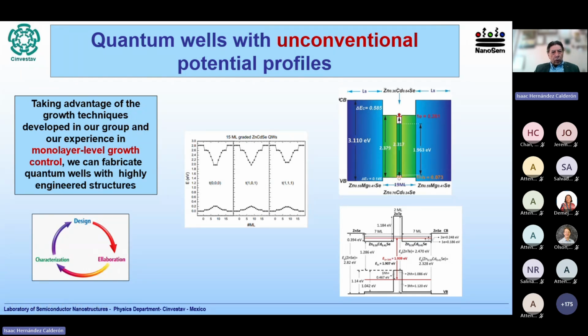So typically what we do is we say we want to have a heterostructure, a quantum well with this kind of specific properties. So then we make a design, we have a methodology, we make calculations, we try to make a design of the heterostructure. Once the calculations indicate that it could be a good structure, then we elaborate it. We do the growth by epitaxial techniques and the characterization. And through this cyclic process, we can refine the properties of the heterostructures. And now I'm going to show you something we have done that's very interesting.